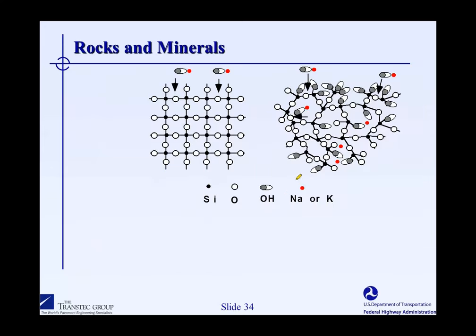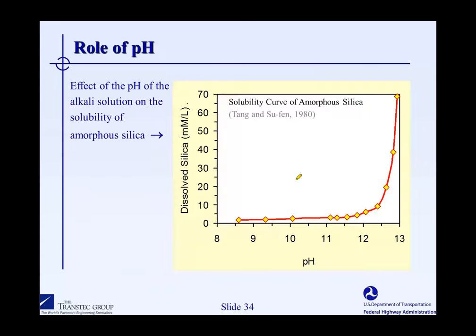So why is that? Well, we really have to look at the crystalline structure of those forms of silica, and that's what this figure shows. It shows quartz on the left and opal on the right. They're both composed of silicon and oxygen predominantly. But whereas quartz is very well crystalline, has a very rigorous crystal structure, which makes it fairly stable thermodynamically, opal is a complete mess. It has a very disordered structure, hardly any crystallinity. You could almost consider it amorphous. And it's this that actually makes it reactive.